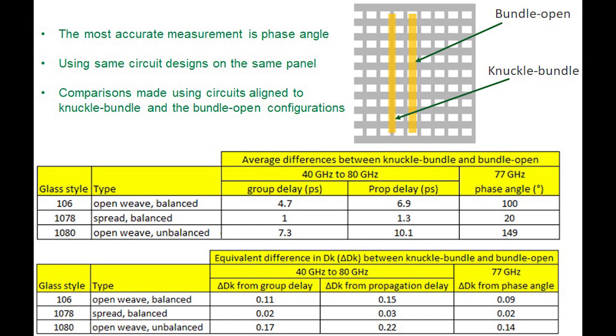Now let me explain the test vehicle and the materials quickly. The test vehicle was a microstrip transmission line that in the signal launch area was 50 ohms, and then we made impedance transformers to transform it to 75 ohms, and we did that to make sure the conductor width was very narrow and much smaller than the bundle open areas, so you could get a good resolution of this glass